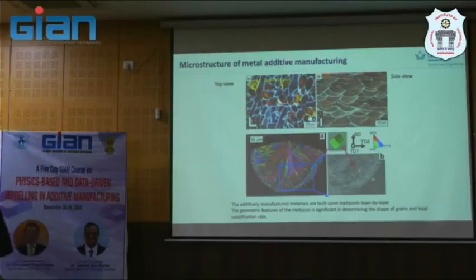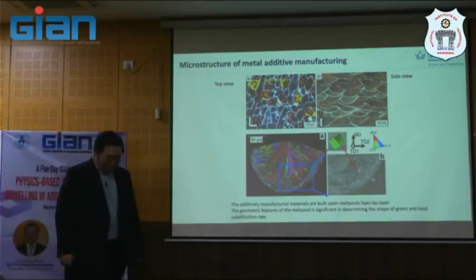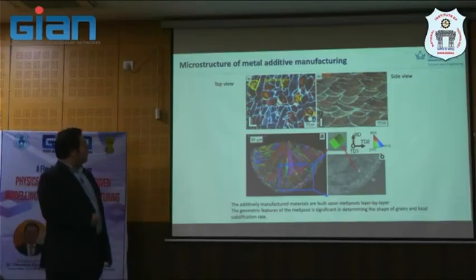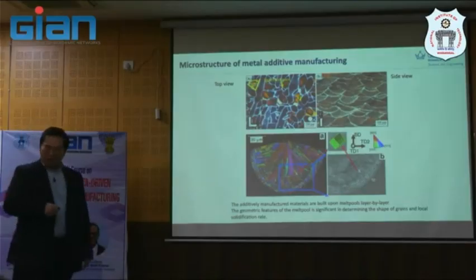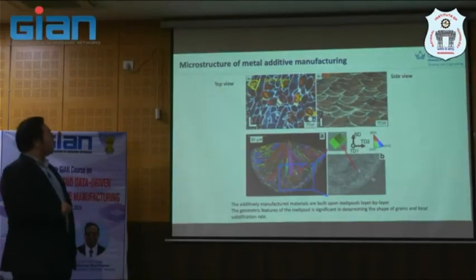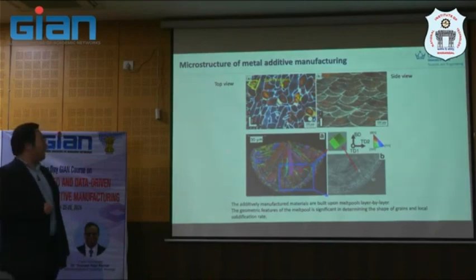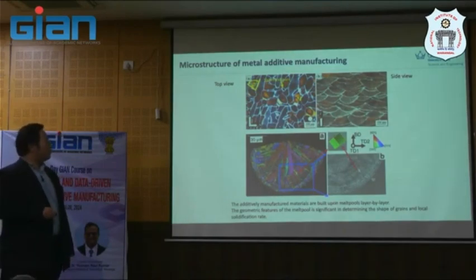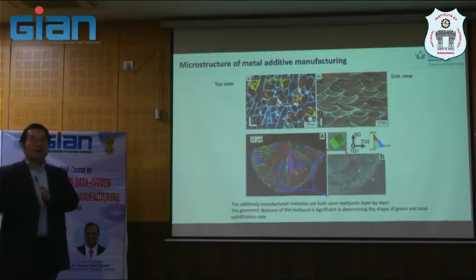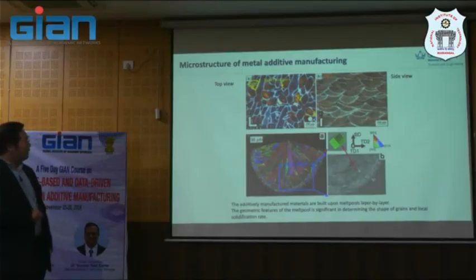Microstructure of the metal. I mean, this is another insight, which, if I'm not mistaken, I'm not sure, is in Nature Communications or Advanced Materials. You will see that this is just one melt pool, but they map at very high resolution. And what you will see will lead to the next topic that I'm going to talk about, which is macrosegregation. You will see that the melt pool boundary here is decorated by equiaxed grains, whereas the transition of the columnar is going this way. So this equiaxed columnar transition happens in this layer.